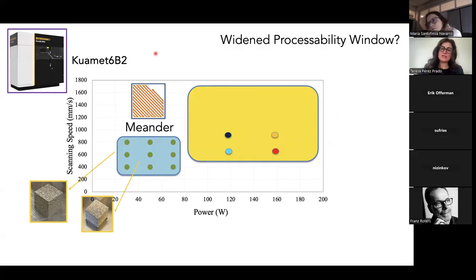Again, I come back to the same processability window that I was showing you before. Just as a reminder, with the simple meander scanning strategy, this blue region was the only accessible region. And now we used another system that we have. This is a Renishaw 500Q. Also a pulse laser. This is multi-laser, but it allows for more flexibility when manipulating the laser beam. So we could introduce time delays with this. And what we did is, let us see whether the introduction of these time delays allows us to access this orange region that was forbidden.